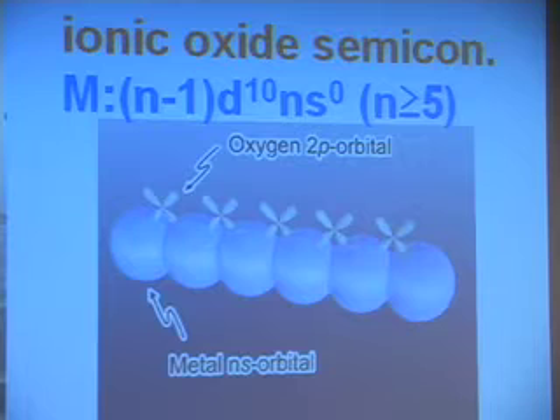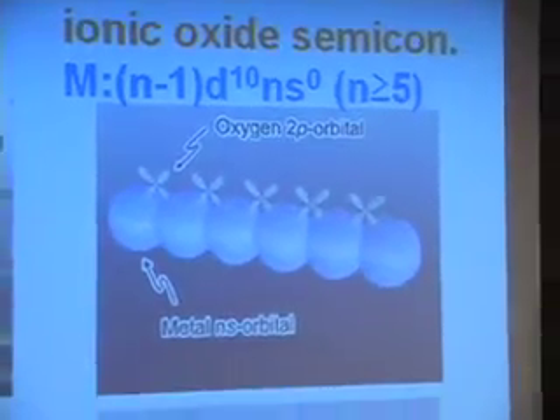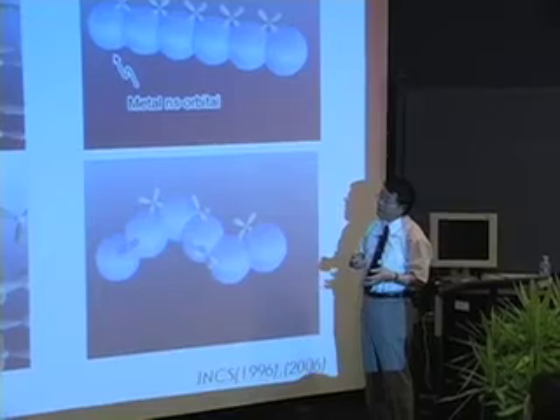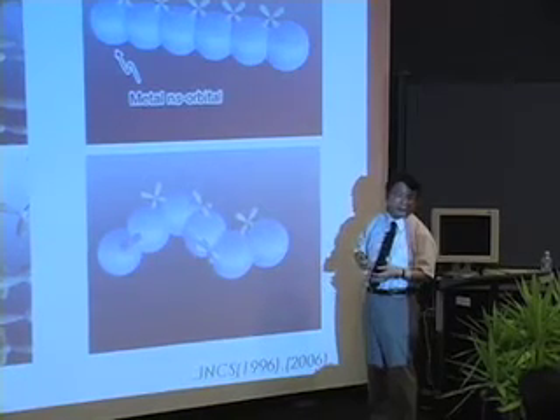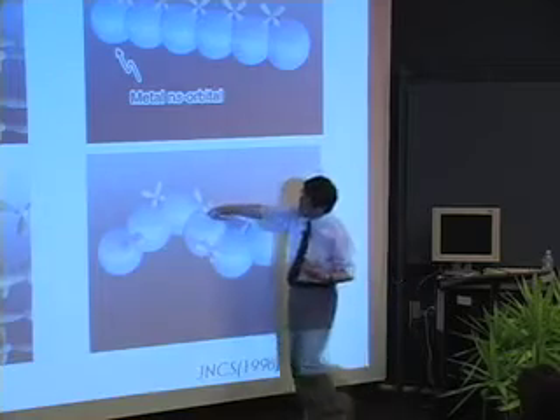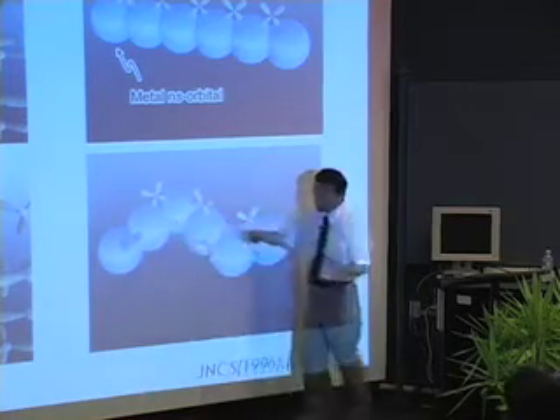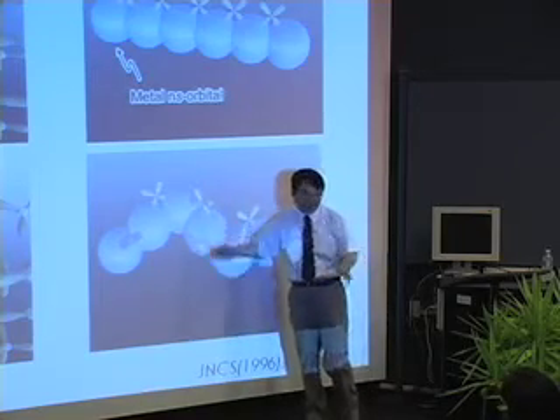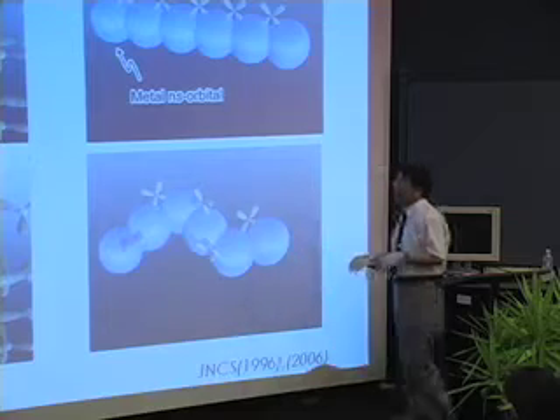The conductivity doesn't change between a stretched state and a folded state. If we choose such a material, almost the same electron mobility should be obtained—this is my idea. The amorphous state doesn't change: crystal is like a stretched state, this is a folded state, so normally the conductivity should be very different. This is a simple idea, and according to this model we examined the material.